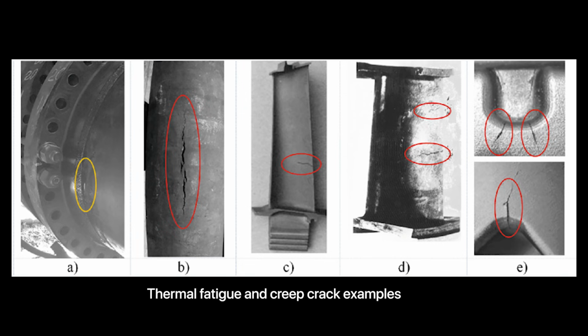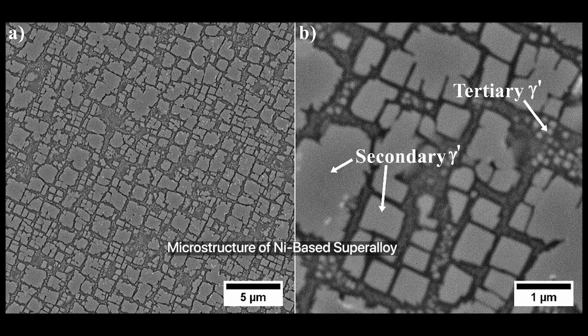The scientists realized that the failure of the blade that happens because of this phenomenon, high temperature and high deformation, is what is called creep. Initially, I don't know, the engine manufacturers might have started with some material, but eventually they came to nickel alloys. And then when they started making nickel alloys, they realized that if it has a polycrystalline microstructure, polycrystalline means that if you're looking at a microstructure, you have lots of grains, maybe hundreds of grains.